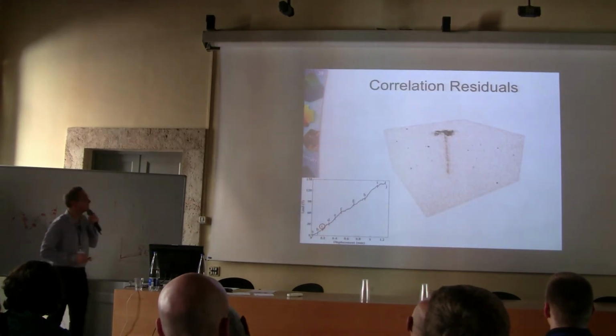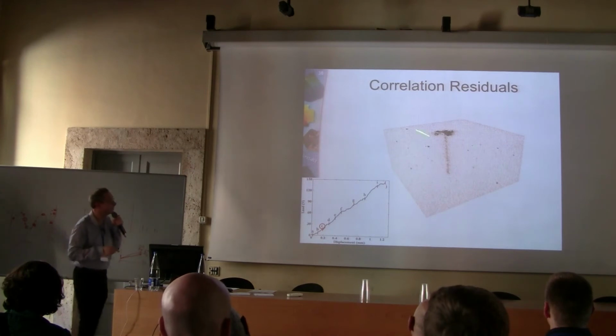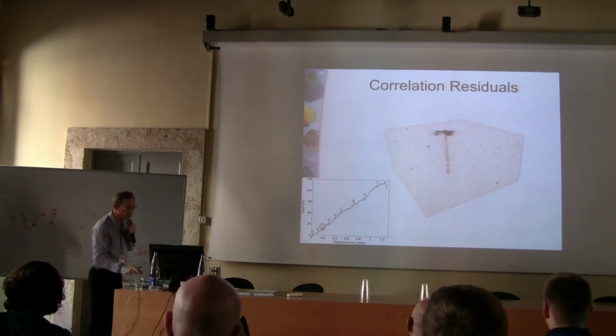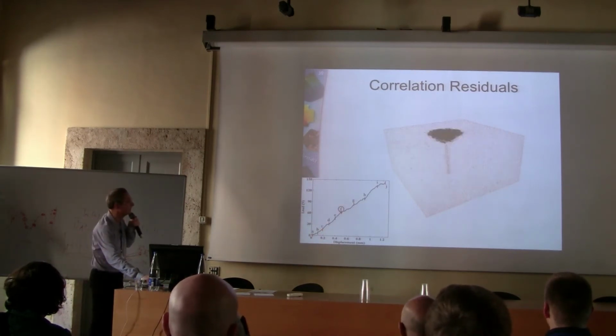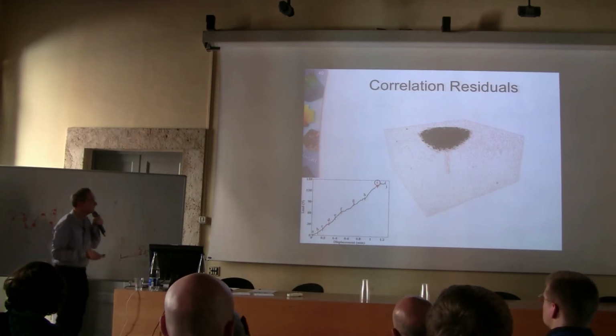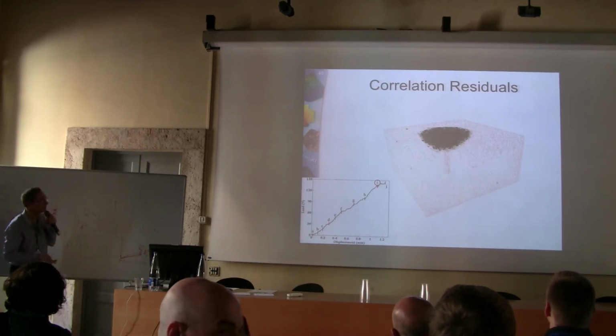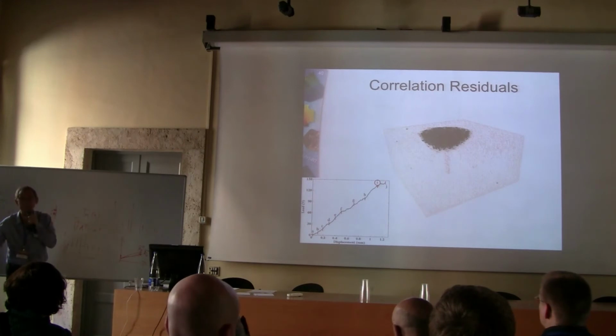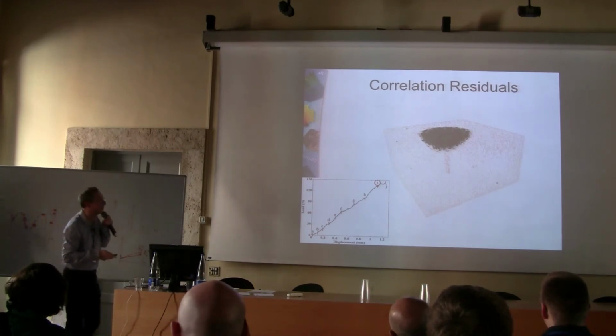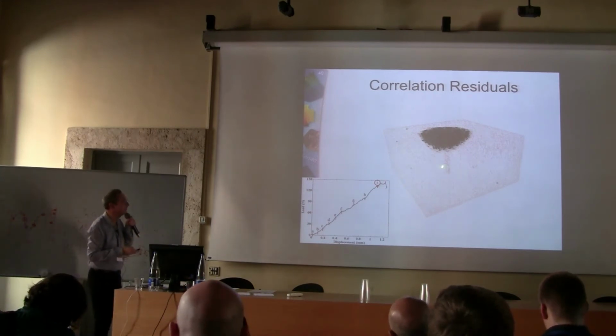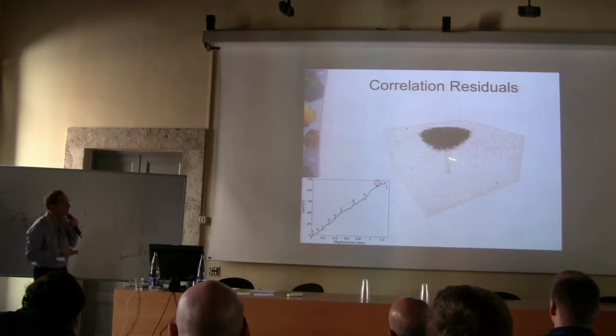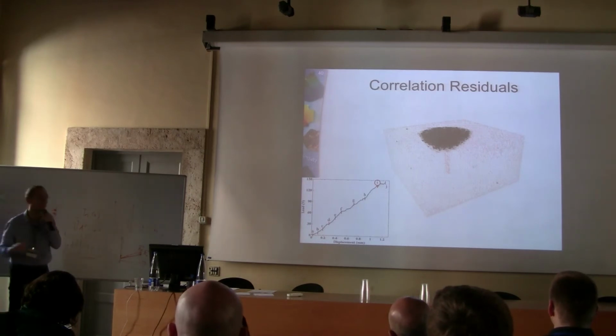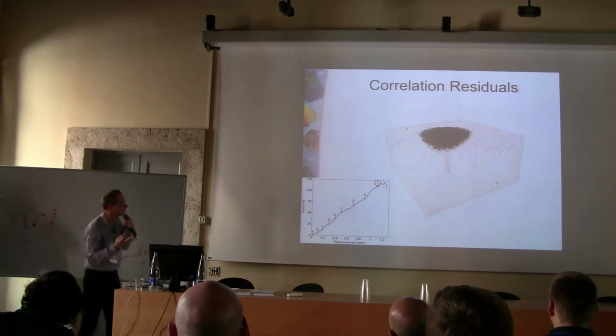Here is a 3D rendering of the gray level residuals for different applied load levels, and you see that basically the crushing zone develops. In the crushing zone, of course, there's no way you can measure meaningful results, but more importantly, we don't see any deviation outside this crushing zone, which indicates that the reduced basis is consistent with your experimental data.